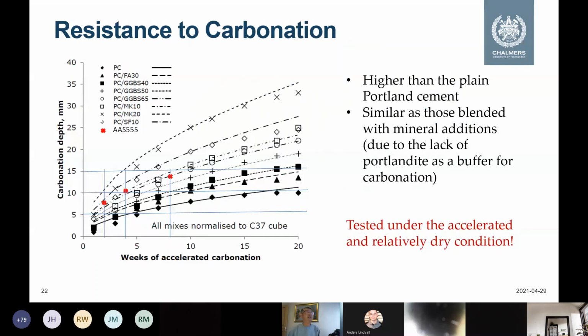For carbonation, this is the result from Rise, which helped us to test it. This red point is alkali-activated concrete. So you can see that in fact we are in the middle. Of course, we cannot compare with the Portland cement. For Portland cement, we know that any addition to the concrete by cement replacement materials will increase the carbonation. So you can see that this is fly ash, slag, and metakaolin, silica fume. So you can see the alkali-activated concrete is in the middle. So this is not kind of strange. I think the main reason is that we have a lack of portlandite, which is the buffer of carbonation, as usual.